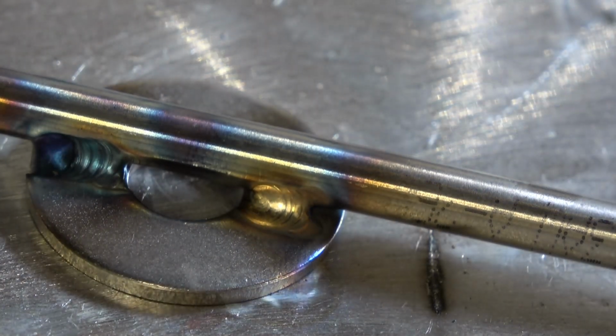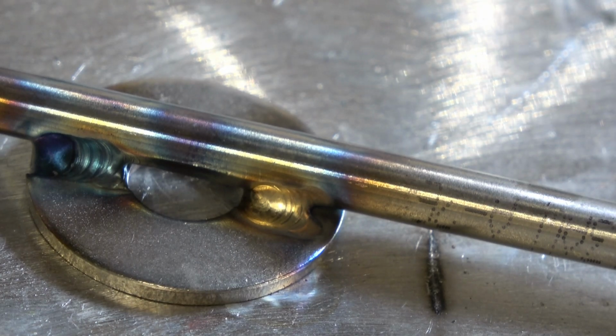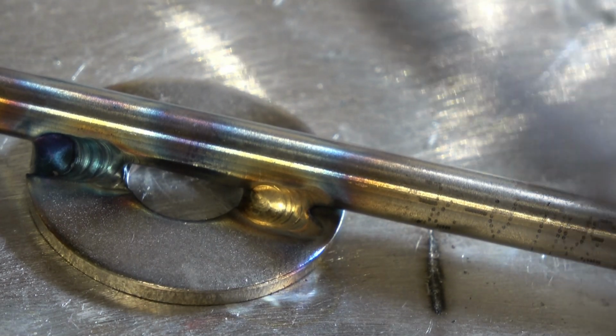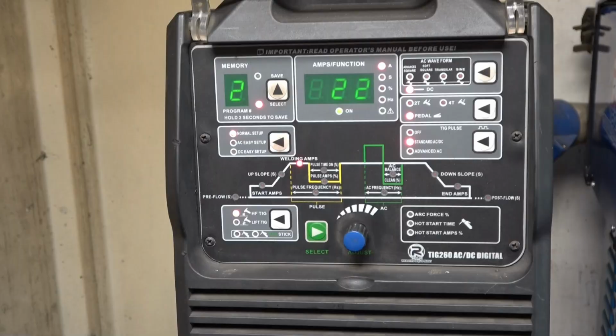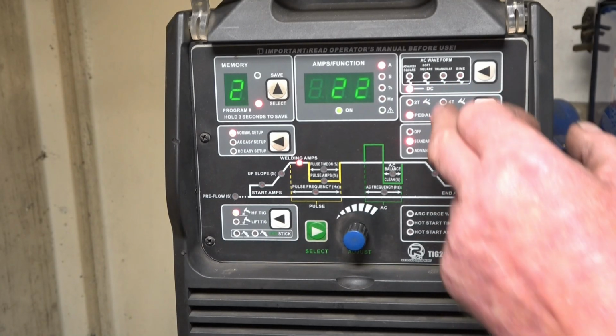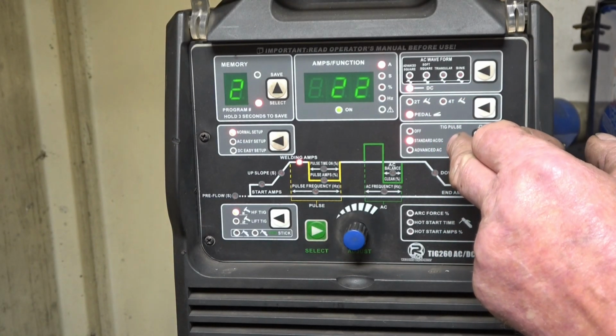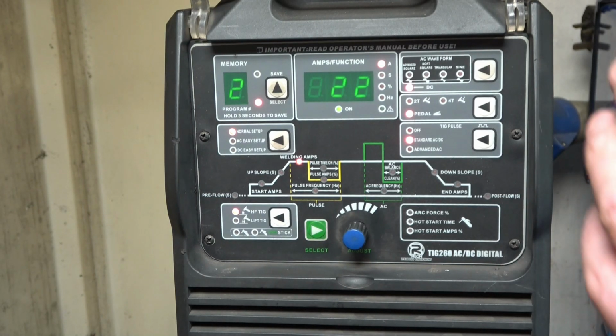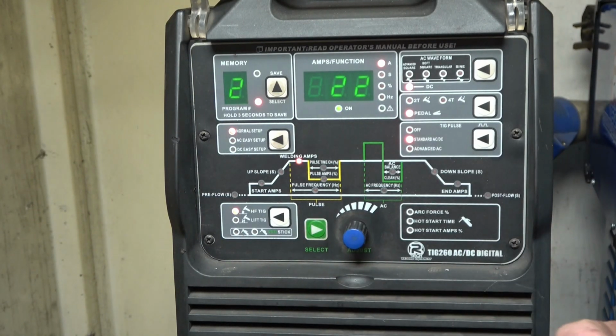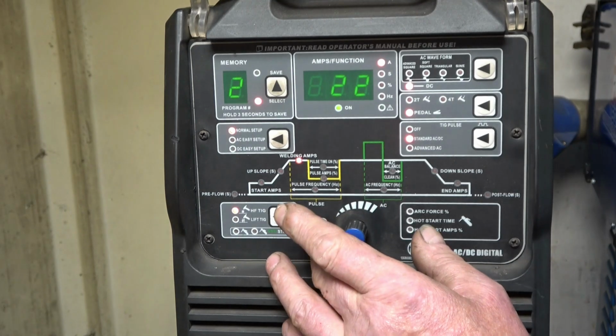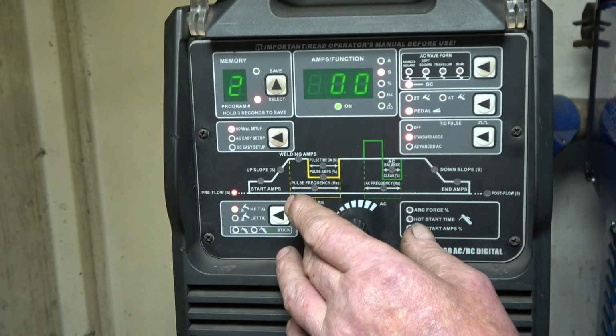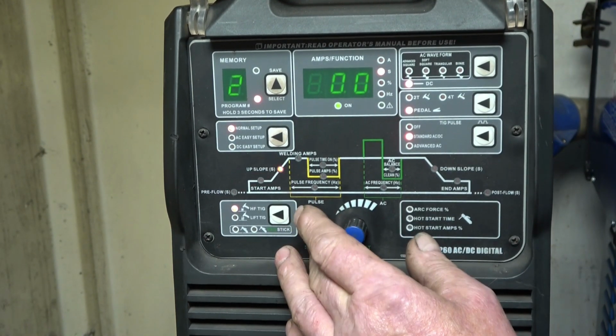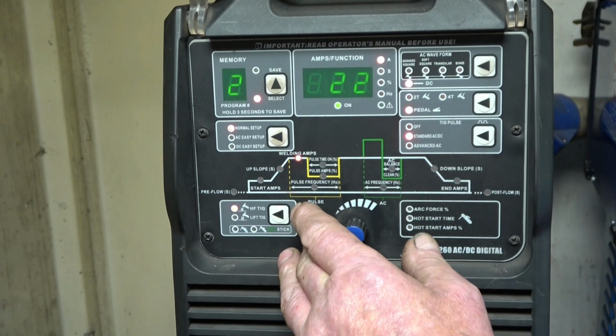I'm going to set another one up and I'm going to use the pulse setting that I use on razor blades and see what sort of result I get with that. Right, we're now on pulse, DC pedal, standard AC, DC pulse. This is what I use to weld razor blades, or at least I've found it works. We'll start off at the beginning as normal. No pre-flow, no start amps, no upslope. I've got my weld amps set to 22.